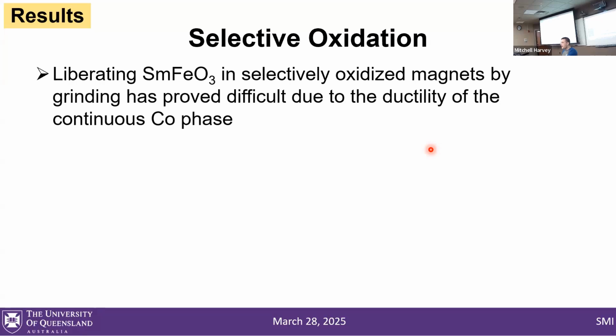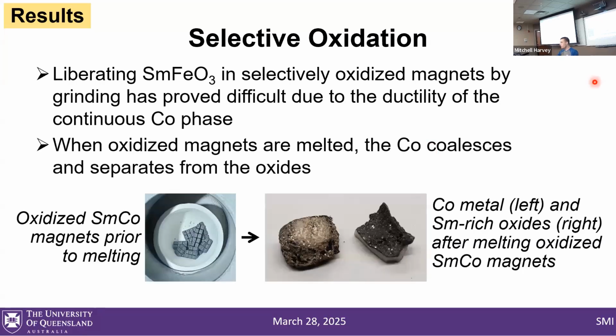So we've had to resort to our backup plan: melting the cobalt. If you heat the cobalt to its melting point, it's going to melt and coalesce into one bead, and the oxides will float to the surface. You let it cool, and you can then break the two apart. Unfortunately, this is a lot more energy intensive—it requires higher temperatures, so it's probably more energy intensive than other low temperature physical separation steps, but it works so far, and this is the best we have to date. On the bottom left, we have our oxidized magnets in a crucible in an induction caster, and on the right, you have the cobalt metal and the oxide that we recovered from it.